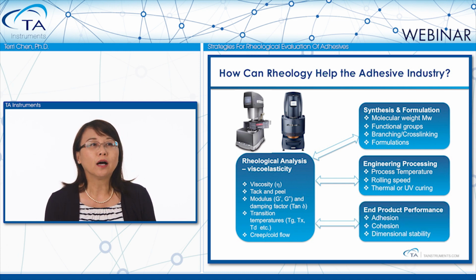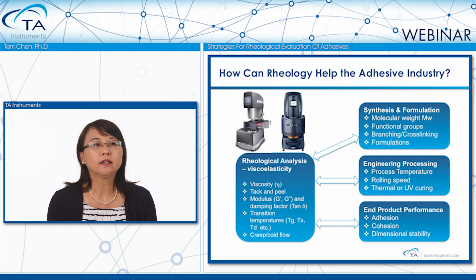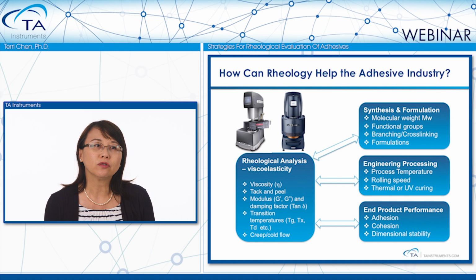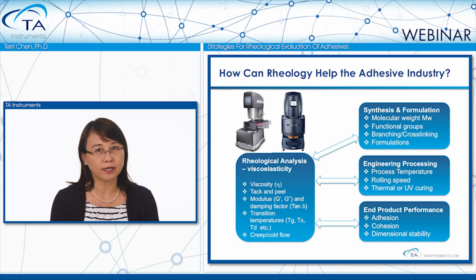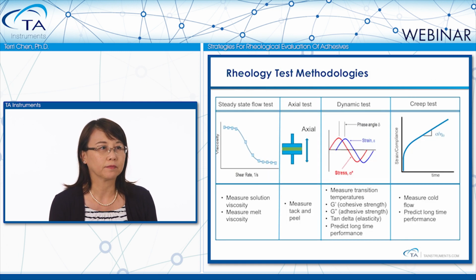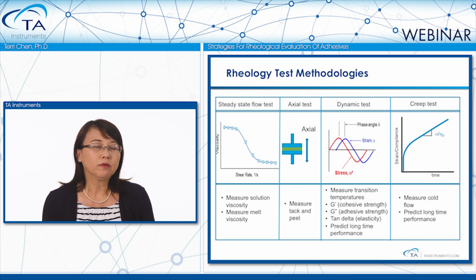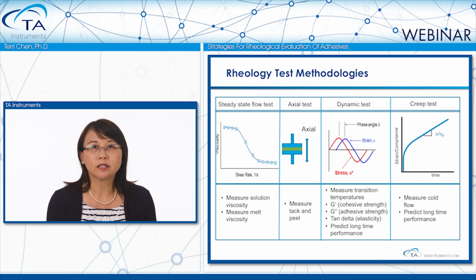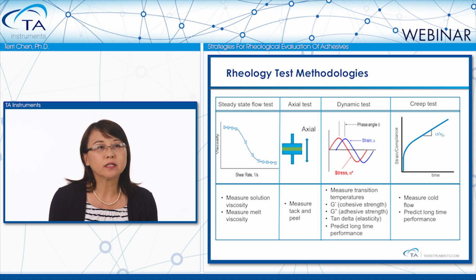In addition, rheology can also quantitatively measure the end product performance. The measured rheological parameters can be used to directly correlate with adhesive, cohesive strengths, and also elasticity. This table listed 4 commonly used rheological tests in adhesive analysis. First, a steady flow test can measure shear viscosity over a wide range of shear rate. The axial testing on a rheometer is typically used for measured tack and peel.